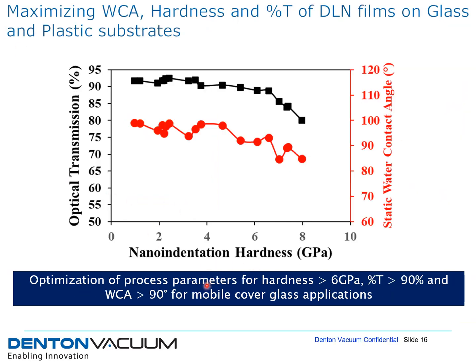One of the applications that we were targeting was hard coatings on glass and plastic substrates for mobile cover glass applications. The coating had to have a hardness as good as glass, so greater than 6 GPa, an optical transmission greater than 90%, and a water contact angle greater than 90 degrees. And this is the summary of the properties that we have obtained so far.